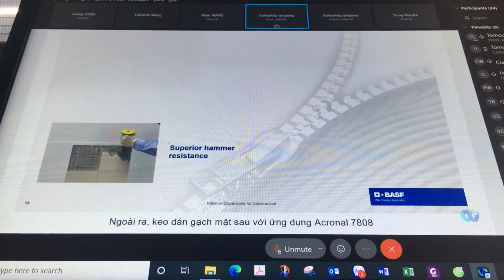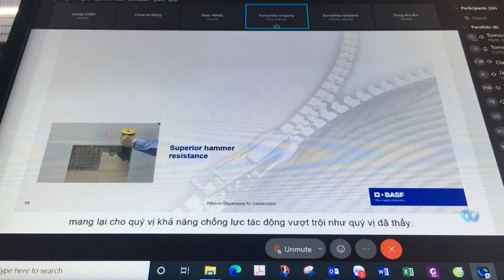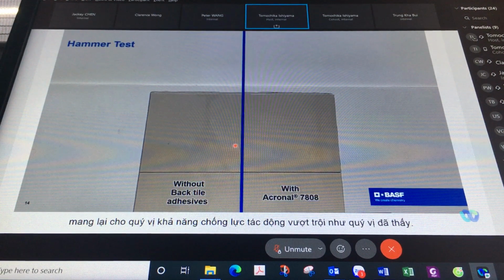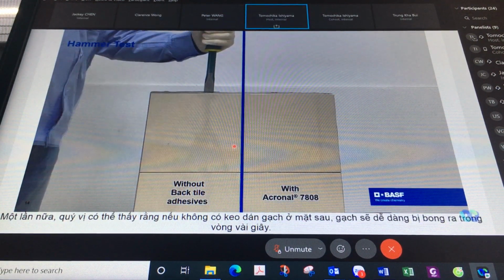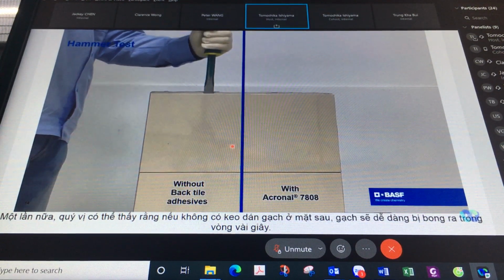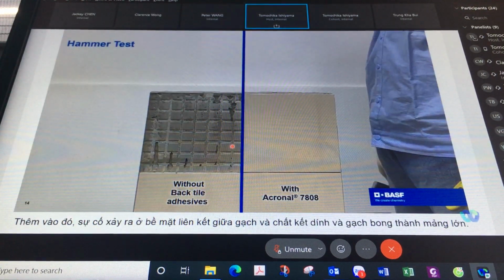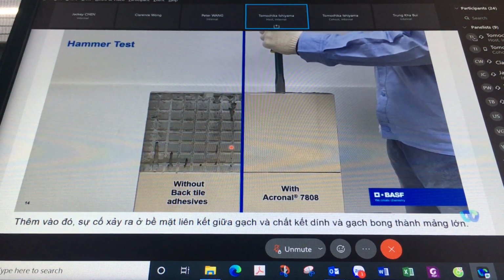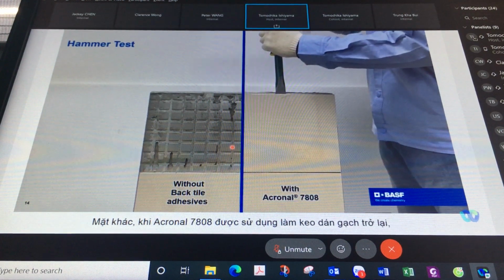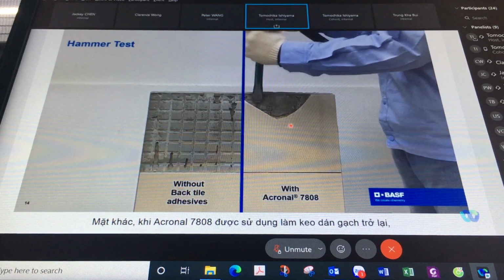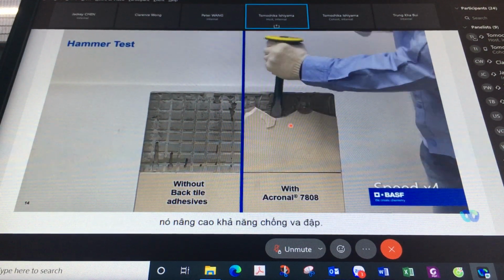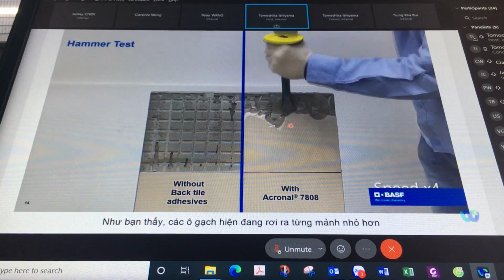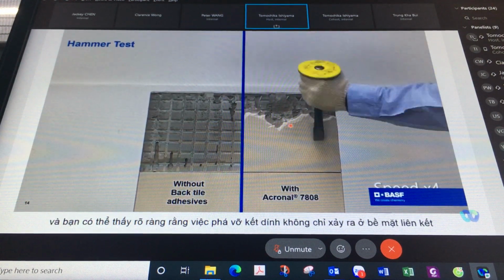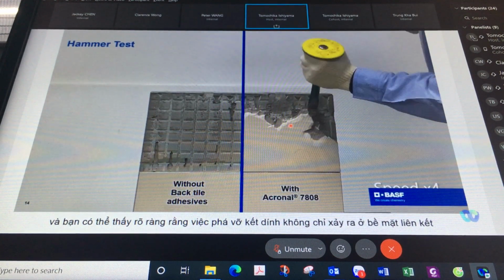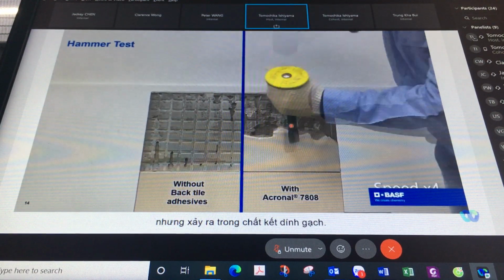Also, back tile adhesive based on Acronal 7808 gives you the superior hammer resistance, which you have seen. Again, you can see that without the back tile adhesive, the tile is easily knocked off. Also, the tiles are in a big piece, and the failure is happening at the bonding point between tile and tile adhesive. On the other hand, the Acronal 7808 is used as back tile adhesive with highly advanced impact resistance. As you see, the tiles are now falling in smaller pieces, and you can clearly see that the debonding is not only happening at the bonding surface, but occurring within the tile adhesive.